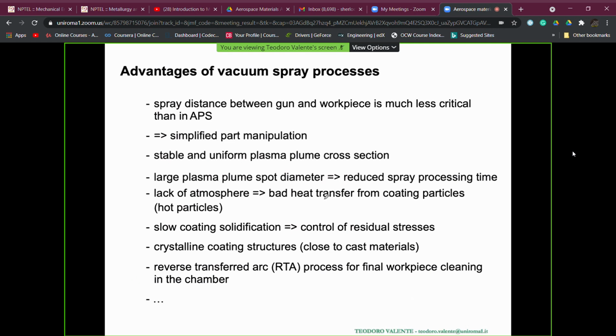But anyway, one of the most important advantages among those which are listed here, some are also disadvantages, is the possibility to have a slow coating solidification due to being in vacuum, with reduced heat transfer after impacts of the particles on the substrate. And this is beneficial in order to reduce and better control the residual stresses on the fabricated coatings, which in some cases is the basic mechanism on which, under working conditions, coatings can undergo failure.